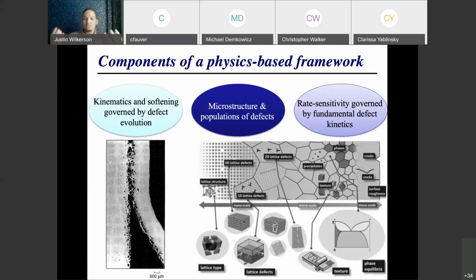So we have this nice physics-based framework, but I don't know exactly where the voids are going to nucleate. I don't know exactly how far they're spaced apart. I don't know what their initial size is going to be, what the size of the second phase particles are that they nucleate from. I don't necessarily always know the dislocation density on every slip system. What fraction of that dislocation density is mobile? What fraction is immobile? So those initial conditions become the most difficult aspect in comparing with experiments.